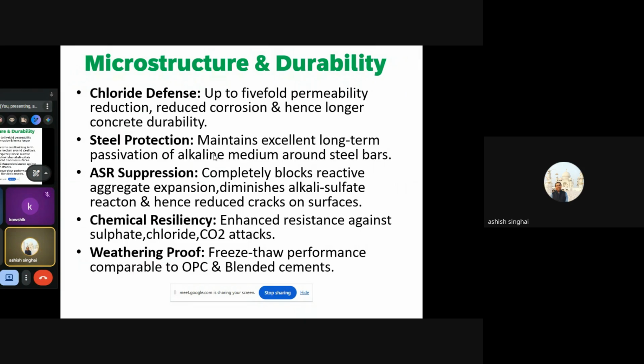So in case of ASR suppression or ASR aversion, what we call it, LC3 also helps. In which way? It completely blocks reactive aggregate expansion. Aggregate also has the capacity to expand because they are chemically reactive sometimes. It reduces the alkali silica reaction and hence reduces cracks on the surfaces. So that is a very important thing. LC3 has that capacity, has that resilience to resist ASR-generated after effects like cracks and wider deep pockets.